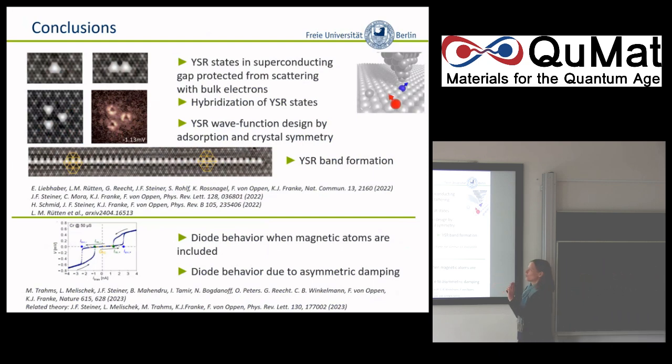Because, I mean, the manganese and chromium, we used them because we saw this asymmetry. And then we were like, oh, is it some artifact? So we used different species of manganese and chromium. It really scaled with the asymmetry of the states. But then we also went to different atoms in different adsorption sites, where, ideally, we thought we could engineer the non-reciprocity. Ideally, I would think we need the largest asymmetry at the lowest energy.